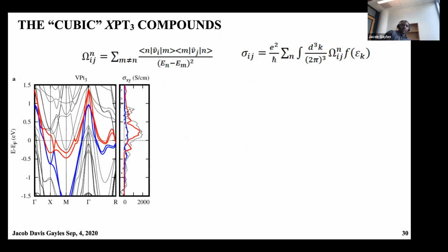We can continue and actually look at these 2 sets of bands for the different systems. So if we take here the vanadium platinum 3, we can calculate the anomalous Hall effect due to these bands, which shows a little bit of reciprocity. And here in the black is the total, the red is from the red set of bands, the blue from the blue, and the dashed black here is from all of the bands below and above these 2 sets of bands. And here you see primarily the anomalous Hall effect is due to these 2 sets of bands using this Kubo formula technique.